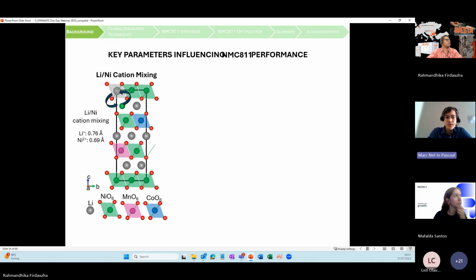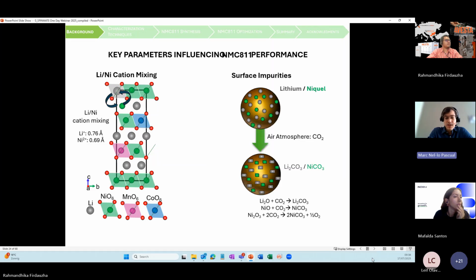So in this case, when you switch these positions, what you are causing is hindering the lithium diffusion and also reducing the capacity of the material. So you are always looking for diminishing this effect. And one of the ways to diminish this effect is by making sure your nickel 2+ is in the minimum quantity possible. Another effect affecting the properties of these NMC materials are the surface impurities.